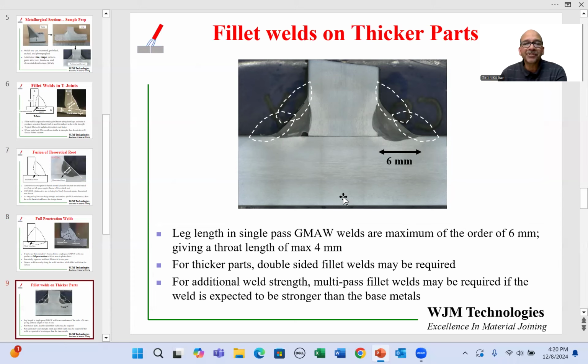So here I'm showing you a cross section of, again, a T-junction where we have two fillet welds, one on either side. Usually, when you use the GMAW process, gas metal arc welding, the largest leg that you can expect from the process and still get good fusion along the legs is 6 millimeters. If the leg length on A and B is 6 millimeters and there's a neutral plane on the outside, you can do the math and you find that the throat is about 4 millimeters. So if this throat is 4 millimeters and the width of this component is much more, then obviously this weld becomes a weak point in comparison to this width.